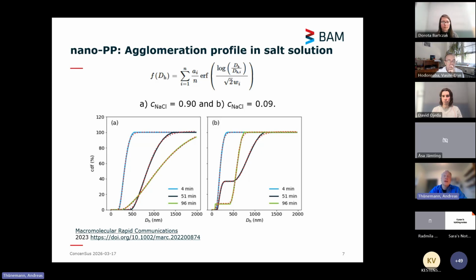But if you add salt, as you expect from colloidal stability, at a high salt concentration of 0.9 grams per liter, the particles aggregate relatively fast. Within an hour, you have about 50% aggregates. If you have a little bit lower salt concentration of 0.09 grams per liter, then the aggregation becomes a little bit more complicated. But when you use the particles in cell culture experiments, you have to be aware that they start to aggregate in your cell toxicology experiments.